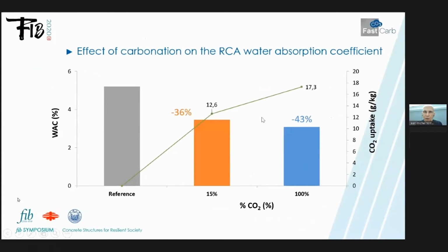A very interesting thing is that we obtain a decrease of the water absorption coefficient, and this high water absorption coefficient is why we need more cement when we use recycled concrete aggregate. So we can expect to save a part of the cement increase with our carbonated recycled concrete aggregates.